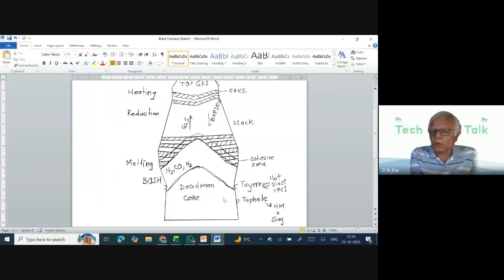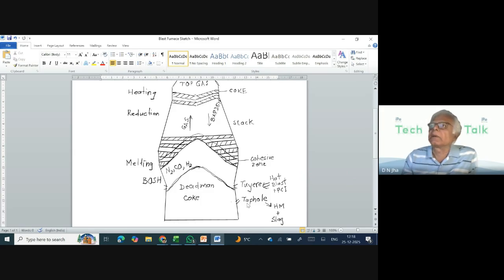So, two things happen here. Because of the high temperature, the volatile material from the coal gets separated, and this is an endothermic reaction because it absorbs some amount of heat to liberate the volatile material. Now, the oxygen available from the blast oxidizes the carbon coming from the PCI and the carbon coming from the coke. Since this oxygen is much lower than the carbon present in front of it, you can assume there is an infinite amount of carbon, and therefore the oxidation does not take it to CO2. It forms only CO.